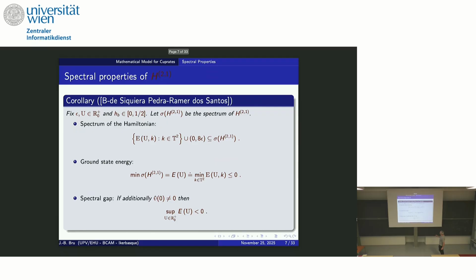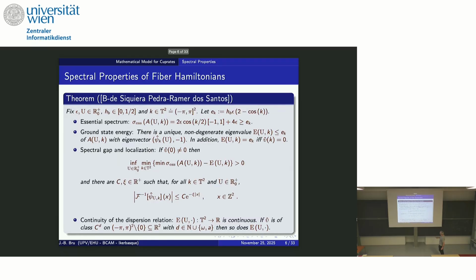Yes, it's just because the exchange interaction makes this bound state. And the U can only be a problem because it can destroy the pairs, but it's allowing to have pairs which are not on the same lattice site. And so if U is very big, it does not destroy the pair. It does not change anything because what makes the pairs is the exchange interaction with boson and fermion. So U has no effect.